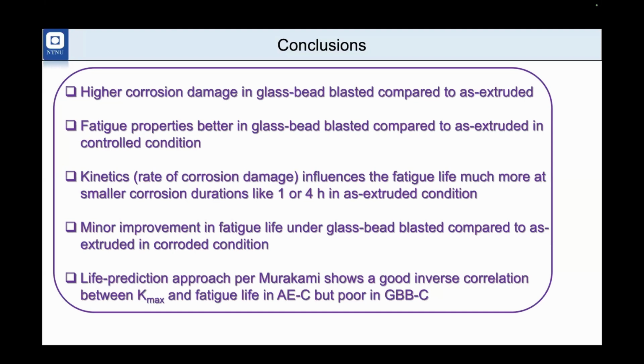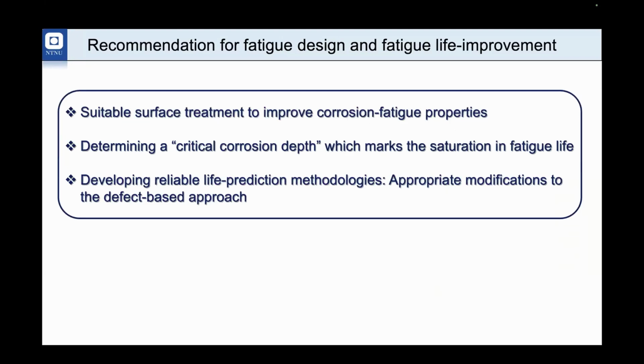And the kinetics of the corrosion damage influences the fatigue life at smaller corrosion durations, like 1 or 4 hours, because you see that beyond 1 or 4 hours, there is a saturating trend in terms of fatigue life. And the life prediction approach per Murakami shows a good inverse correlation, but not so in the case of the glass bead blasted condition.